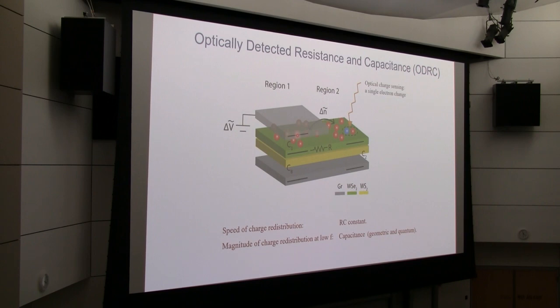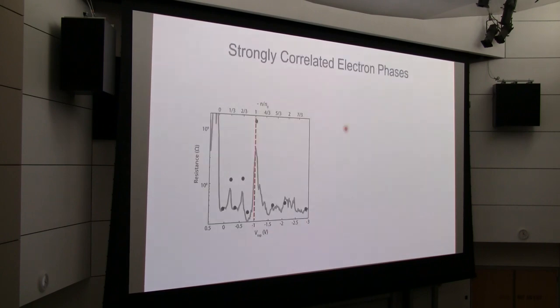So what we can do is measure the density change at this point, in response to our AC gate voltage. And the magnitude of this change tells us how many electrons have moved. So that tells us about the capacitor. And the speed of this change tells us how fast it is responding. So it actually tells us the RC constant of the circuit. So combining these two, we can determine both the resistance and capacitance using pure optical detection. And that works quite well.